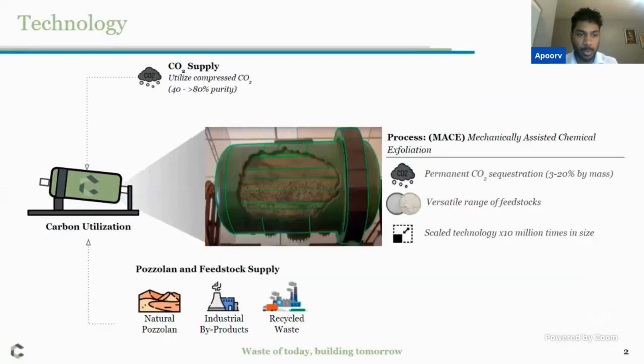Generally speaking, what we've found with our catalytic milling process that we've developed over the last 6 years is that we're able to chemically activate a range of different pozzolans. These could be mine tailings, natural pozzolans that are mined from open pit mining, or a range of industrial wastes, such as but not limited to fly ash or blast furnace slag. And we can activate them to capture CO2 while also significantly improving surface area and reactivity, all in a single step unit operation that you see in the middle of the screen here.